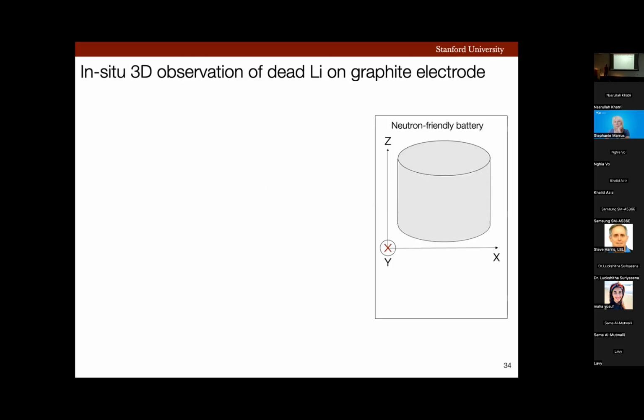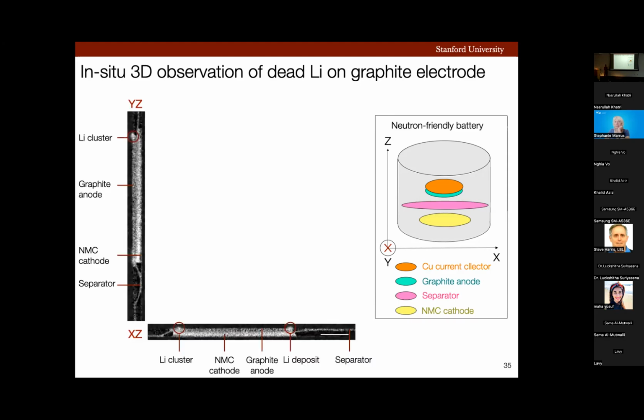Now, before we look into the data, let's revisit the schematic of the battery and see where different battery components are physically located. So in this battery, we have a copper current collector, and then graphite anode, then we have separator, and we have NMC cathode. Now let's look at the cross-sectional XY, XZ, and YZ images. In these images, we can see this line corresponds to the separator. Anode is on the top, and then NMC cathode at the bottom. And we see these brightish clusters on the side of the graphite anode in this cross-section XZ image, which correspond to lithium deposits. This cluster in the YZ cross-sectional image also belongs to lithium deposit, which we can see very clearly in this top view or XY video.